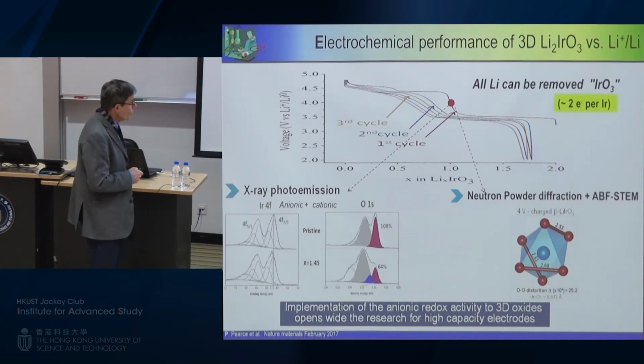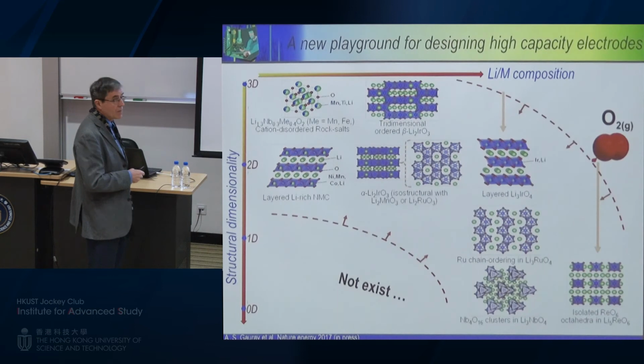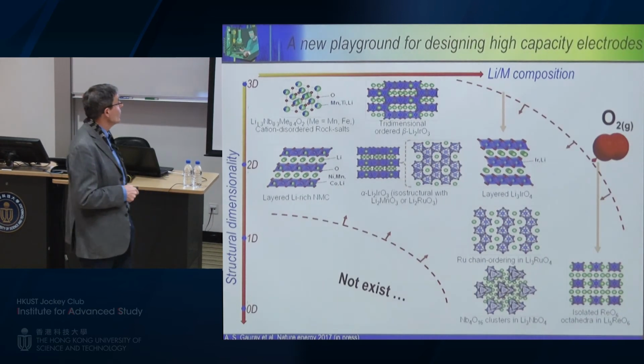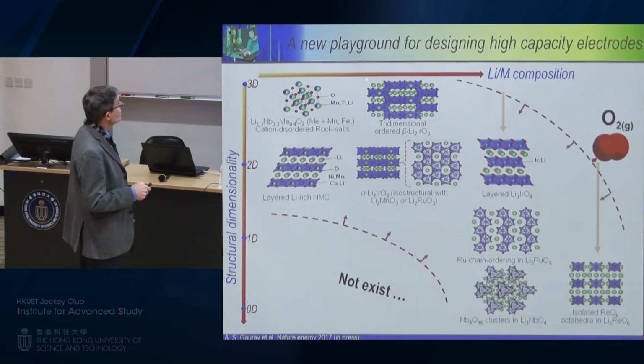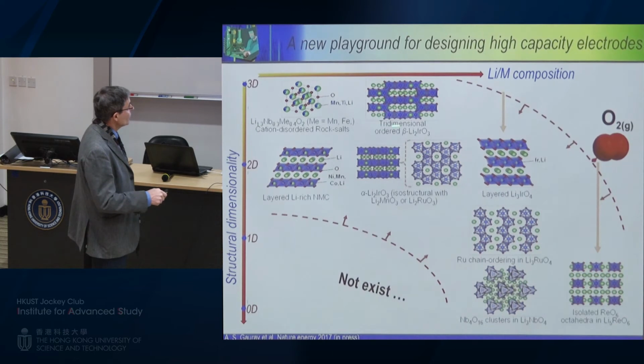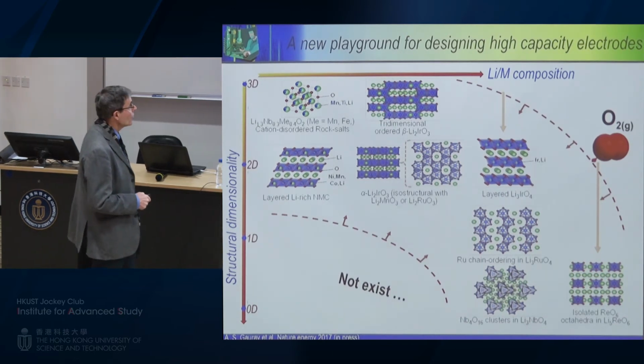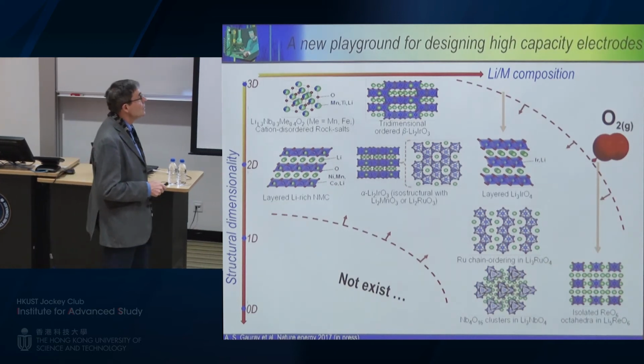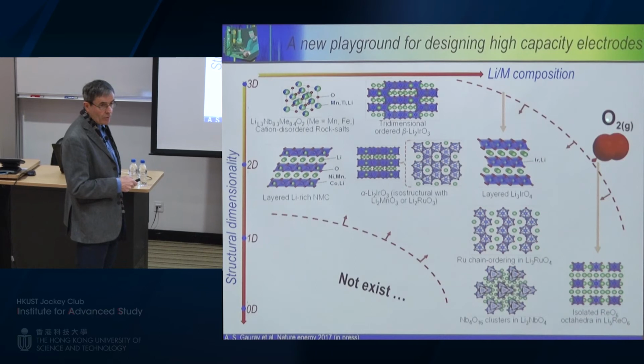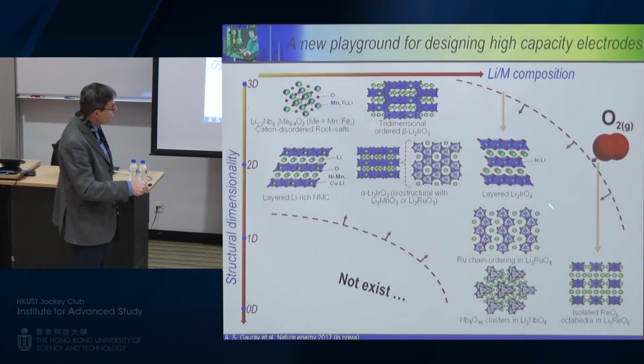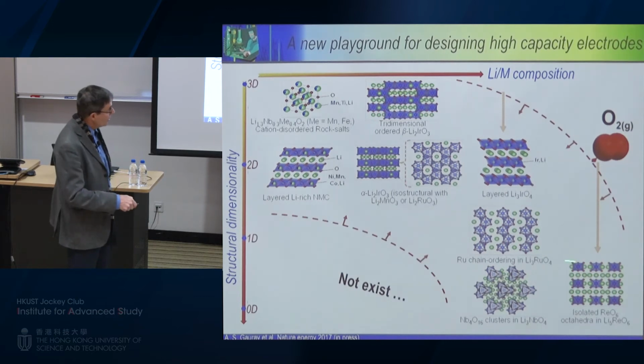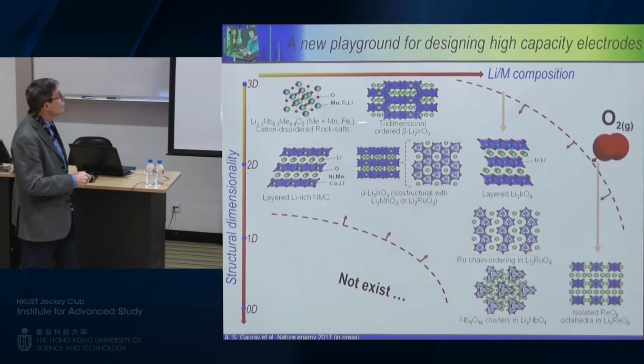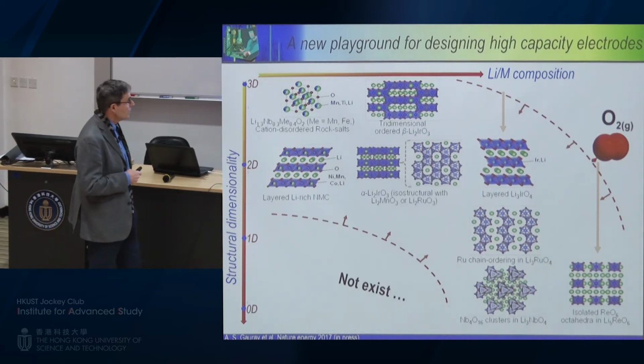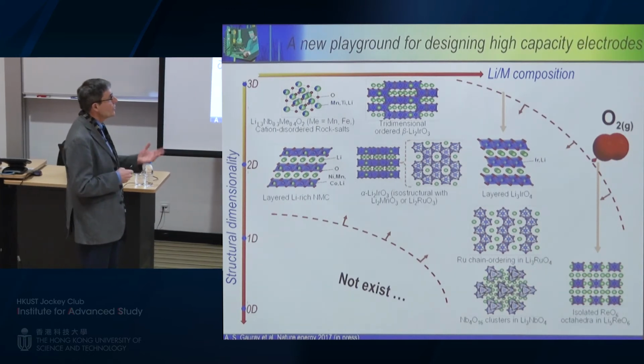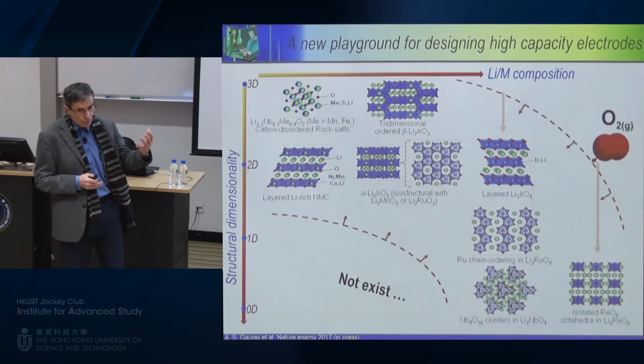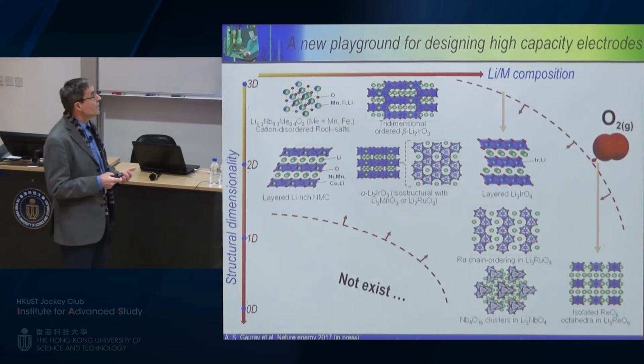And indeed, doing this type of work, we totally open, I will say, the highway, where now we can play with structural dimensionality, we can play with lithium M composition, and you can see more or less all the types of phases that can be synthesized. Of course, remember, I told you that if you want to be too greedy, we can get large capacity, but we have oxygen release. Here, nothing is happening. And of course, if we go here with very high lithium M composition, you fall into the regime of solubility and so on. So you want to stay around there in order to prepare these new materials. So this is more or less what you can do with lithium compounds. Now, can you use these materials for other applications, and can you do something else?